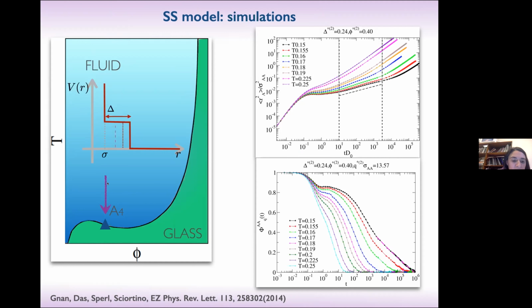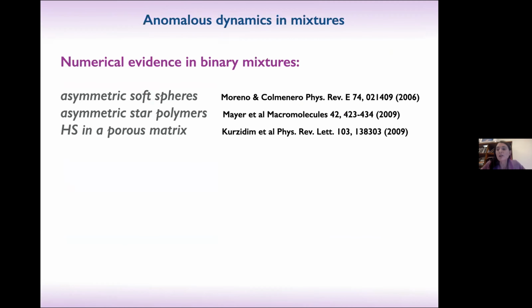And this is due to the fact that, when we come here, there is this liquid-glass transition that the system feels before going to the fourth-order singularity, because the line is not like that. There is this shoulder. And the fact that there is this shoulder in a way kind of masks it at the beginning. So if you simulate up to this temperature, which was not close enough to the A4, you would not notice that there is a logarithmic dynamics. But if you go asymptotically close and are able to bypass the effect of the liquid-glass transition, you start to see this behavior. So actually, all of these results gave us great confidence that there are these higher order singularities in MCT that really have a counterpart in simulation and experiments, and stimulated a lot of work in the last decade.